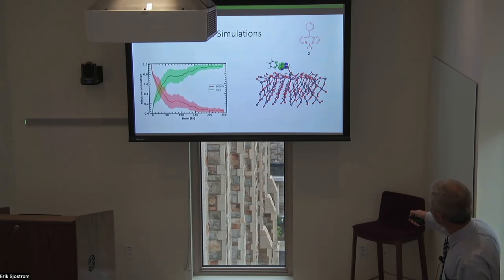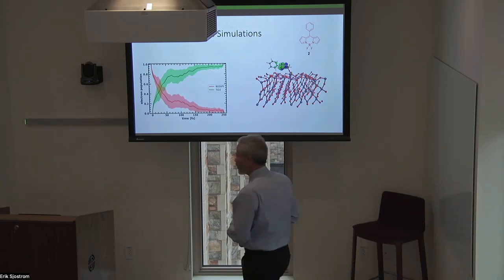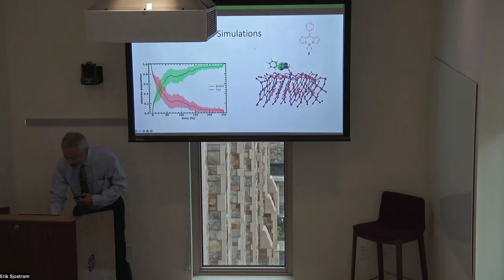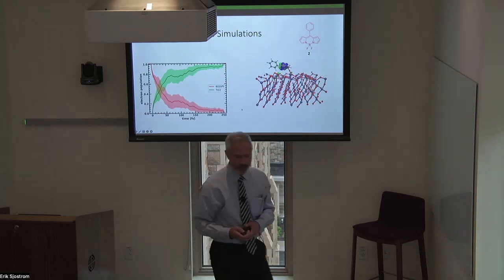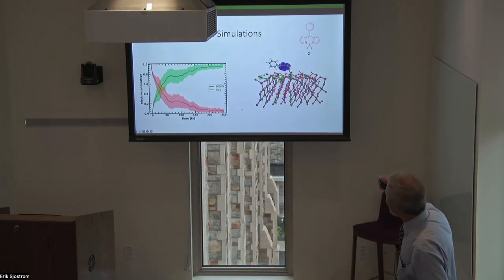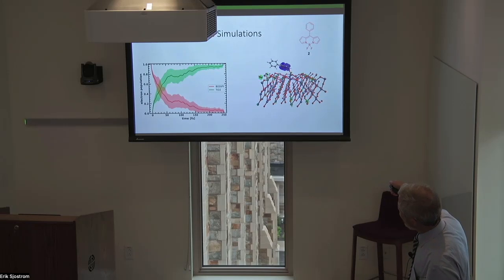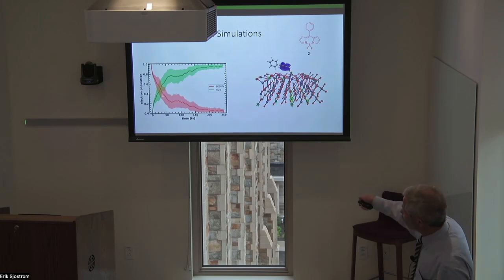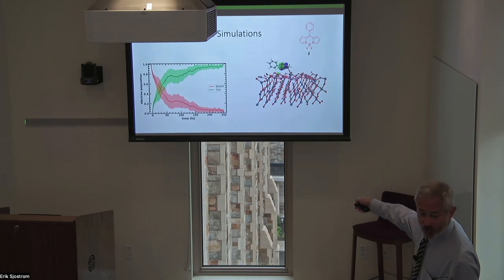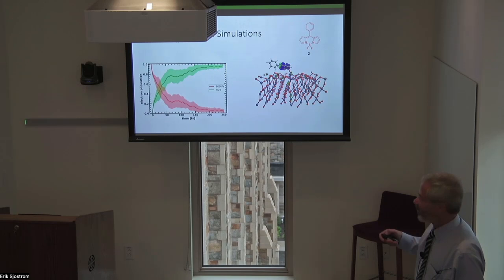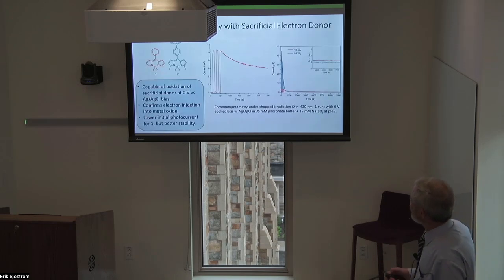And here's a little movie showing the electron injection. Here you can see it injects initially to the interfacial titanium ions that are near the surface, and then it distributes throughout the lattice in the conduction band. And this is happening, you can see, on a tens of femtosecond timescale. So this is ultrafast injection. And so this is really exciting.